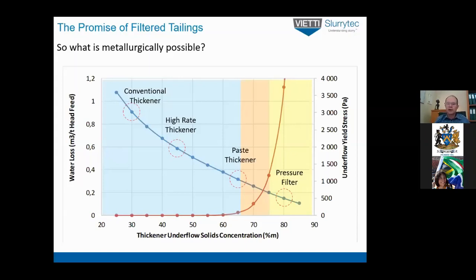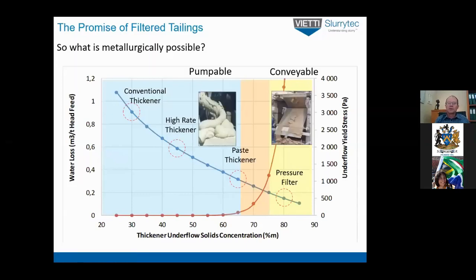You can get way down to high percent solids, 80% solids, and massive water recoveries with a pressure filter running at about 10 bar pressure. And in this case, your yield stress would be in the order of kilopascals. So that's now thick enough to go on a conveyor belt. So we've got two extremes now. You've got paste thickener, which can give you something where you can still use a pump, but on the pressure filter side, pumping is not an option anymore, and you have to go conveying.